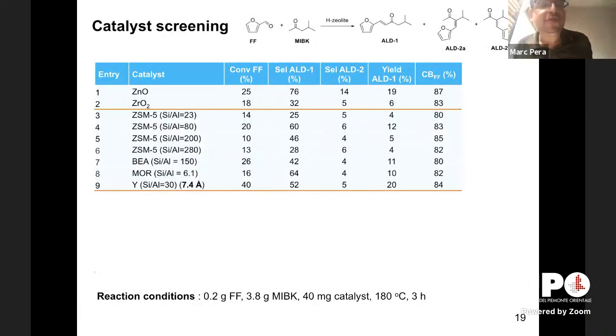So with the support of our colleagues from UPO in Italy, we prepared different zeolites. Here, these are just commercial zeolites, the first ones we tried, just to show you that the yields in the conversion are low, except Y-type zeolite, Faujasite-type zeolite. When the aperture is higher, when the cavity is higher, 7.4 angstrom, the conversion apparently is higher. So it seems that this pore accessibility is something important to run this reaction.